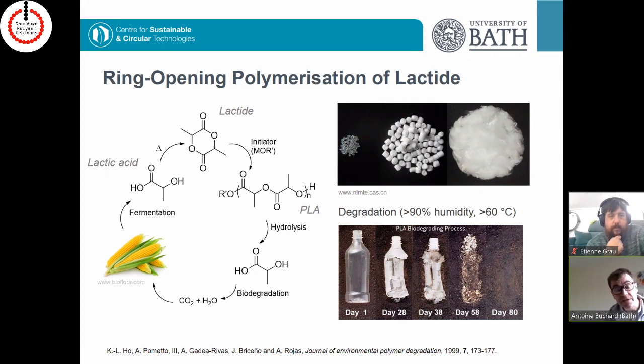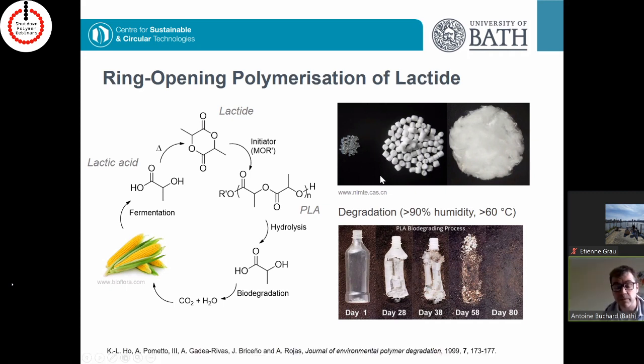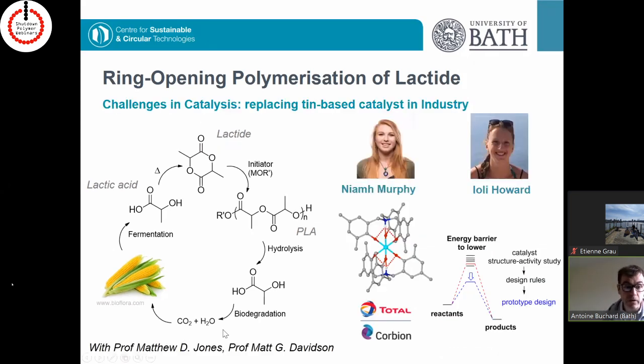Even if you can get lactic acid from glycerol, for example, there are a lot of other ways you can get lactic acid. And this material is great because you can process it in a variety of ways. You can make fibers, you can get foam, you can make pellets. And it's interesting because it is also an industrially compostable polymer. It's not going to degrade in the natural environment, as far as we know, but under certain conditions it will degrade a bit more than, let's say, your traditional polyolefin. And this is something we work on mainly on the catalysis side of things.